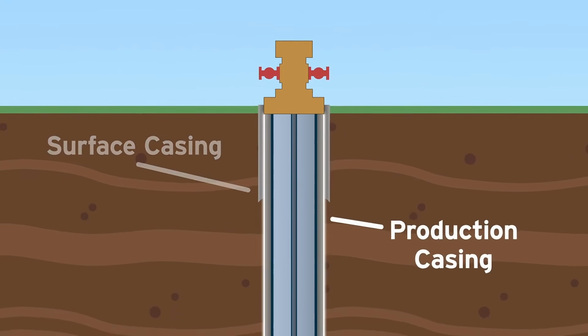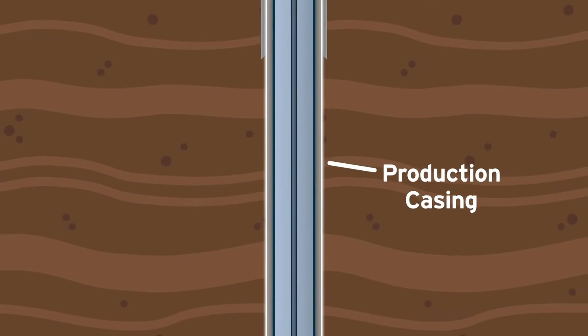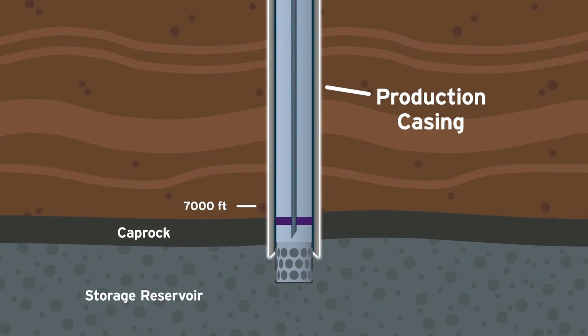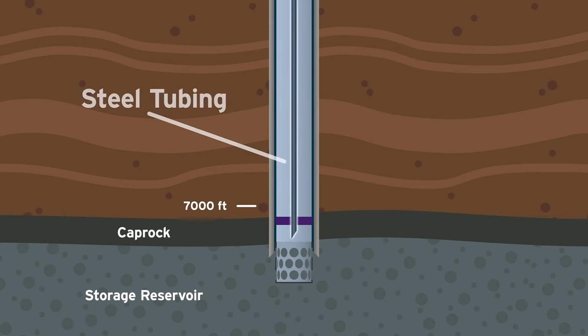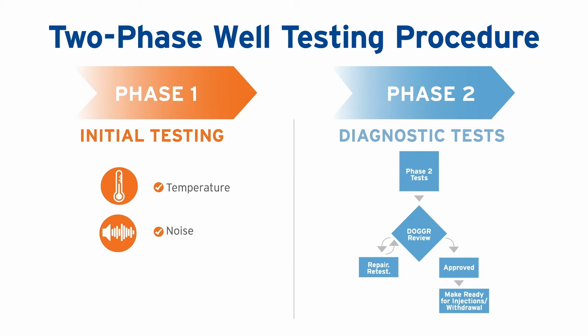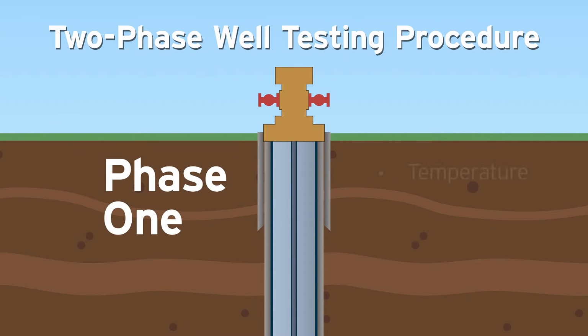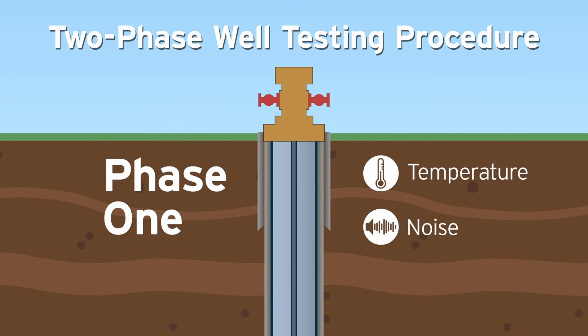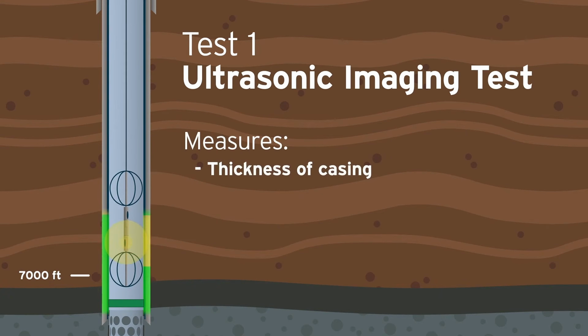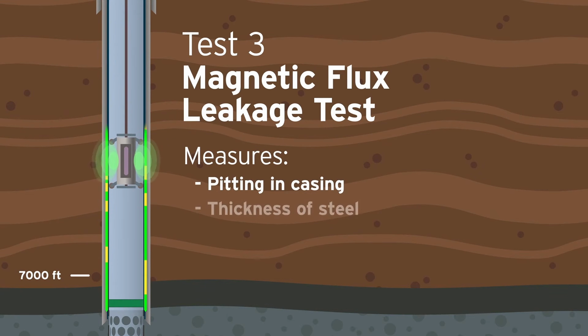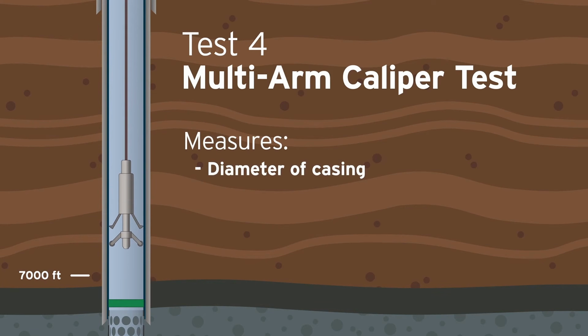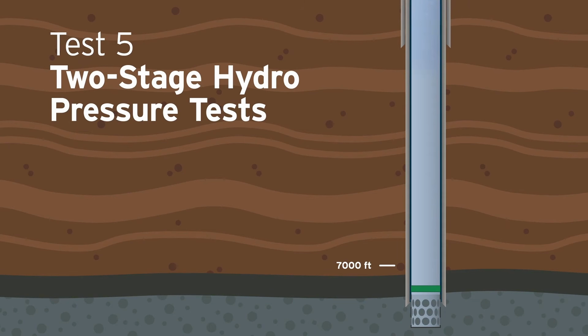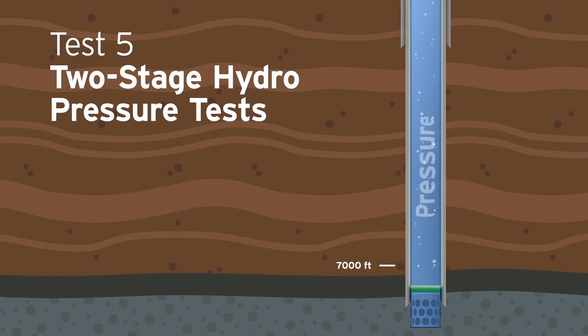How do you compress natural gas or hydrogen into a storage cavern without exceeding the limits of temperature, pressure, and equipment? Before gas ever reaches the cavern, the well goes through every test engineers can throw at it. Two-phase testing runs, temperature logs, noise mics on the wireline, ultrasonic imaging of casing thickness, cement bond checks, magnetic flux leakage scans for pitting, multi-arm calipers for internal diameter, and hydrostatic pressure tests above maximum operating pressure.